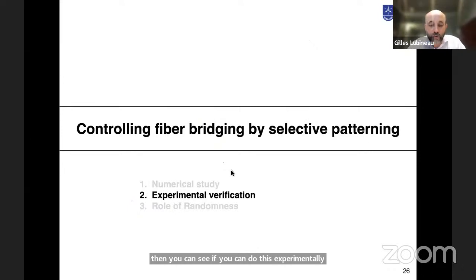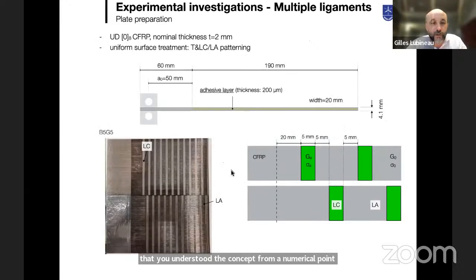Now that you understood the concept from a numerical point of view, you can introduce some experiment. And this is what you can see here. So what we do is that we are taking 2 composite plates, and on each composite plate, we introduce this kind of local laser treatment. So that means you have 2 treatments here. You have a dark green that is going to introduce high toughness, high strength. And then in between, you just have a surface cleaning.